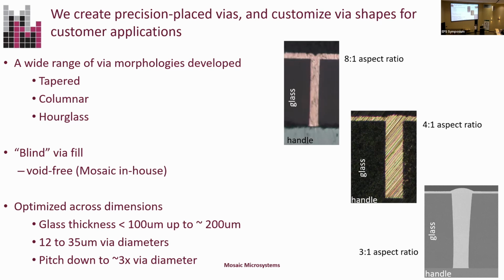And the vias that we've demonstrated so far range from about 10 to about 35 microns. We find that the maximum of 35 micron via is advantaged if you're going to fill it with copper, which has a high CTE. We find if you don't make the vias too large, then you don't end up with any cracking or any issues, even with thermal cycling. So we try to limit the size of the via. And we can do pitches down to about 3 times the via diameter.